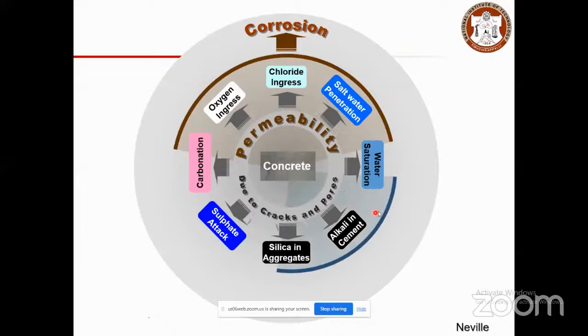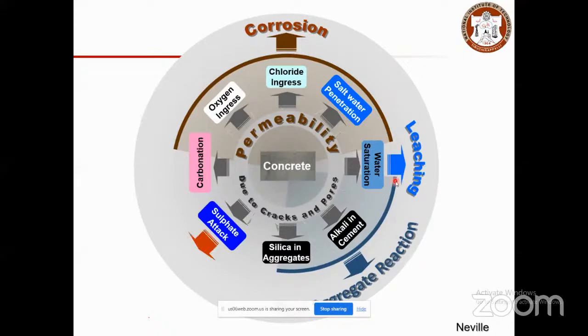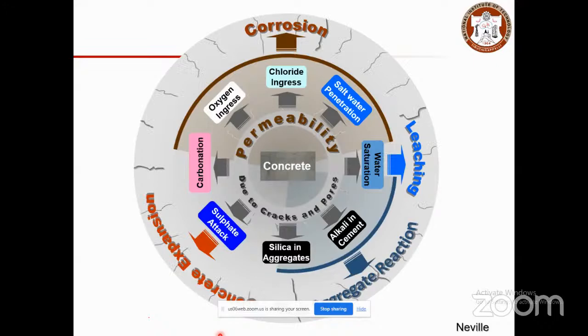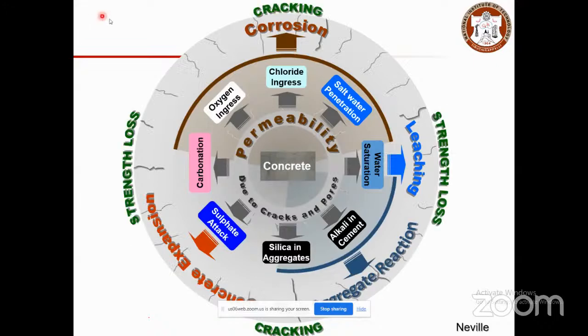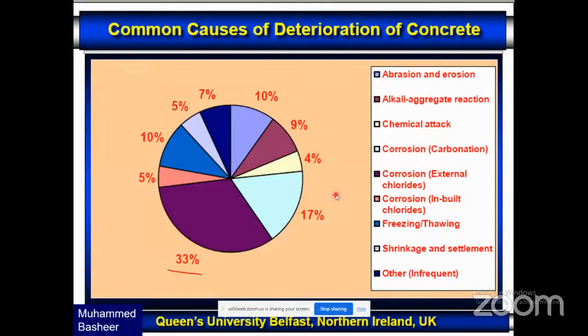Whereas if you look at the water, alkali, silica in these combinations, this may result in alkali aggregate reaction, ASR conditions. On the other hand, if you have only the water saturation, that may result in leaching, and when you have sulfate attack, that may result in concrete expansion, and eventually that is going to crack your matrix. So the cracking will result in strength loss, and once that is lost, the material is going to slowly deteriorate.